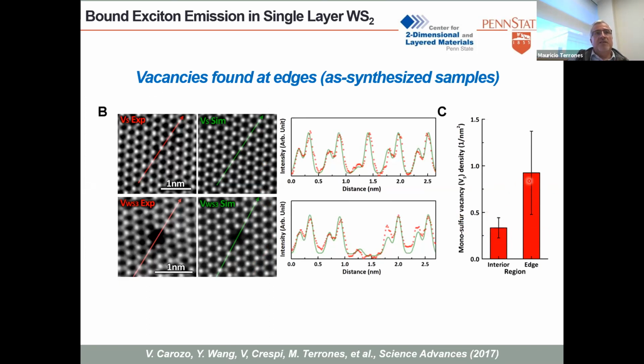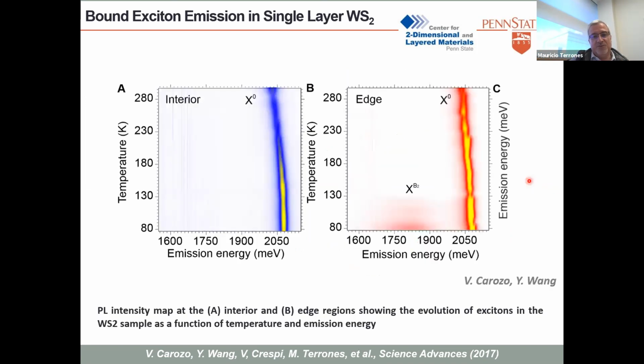and we can see that there is a significant increase at the edge. So this was an easy way to show that you have excitons that at low temperature bind to these defects, and at high temperatures they don't, right? But you can identify these bound excitons to these defects. There are other defects, and things can get very complicated, but this is just to show you. And this is the behavior of the neutral exciton.